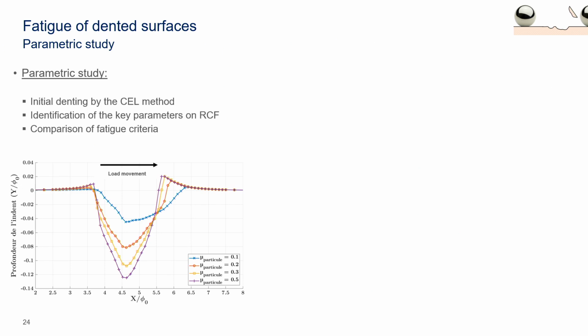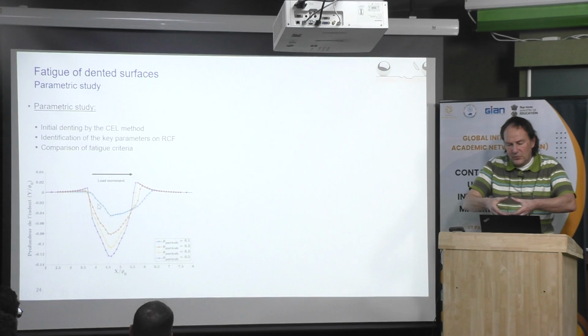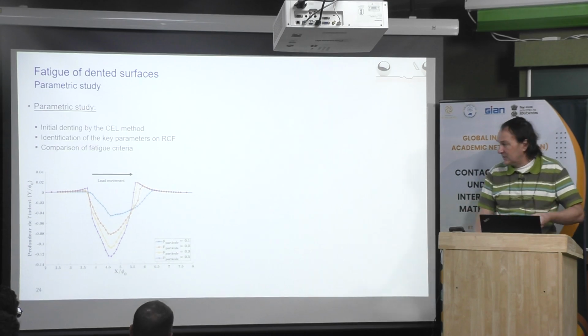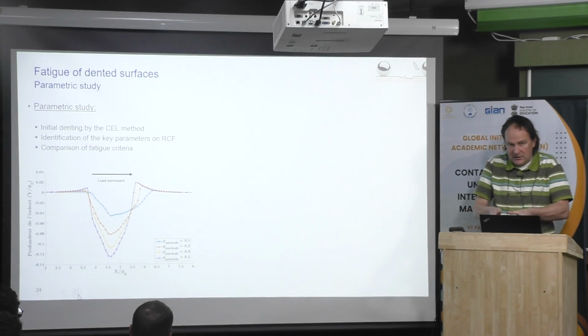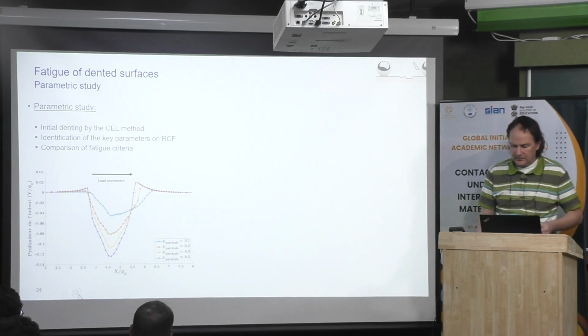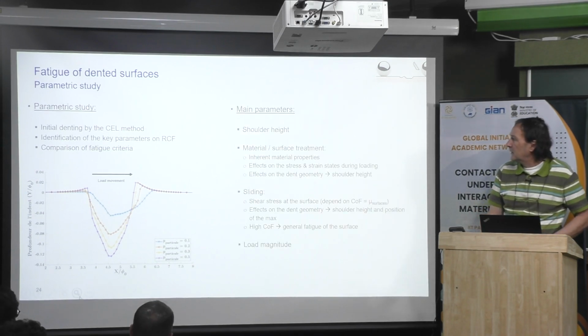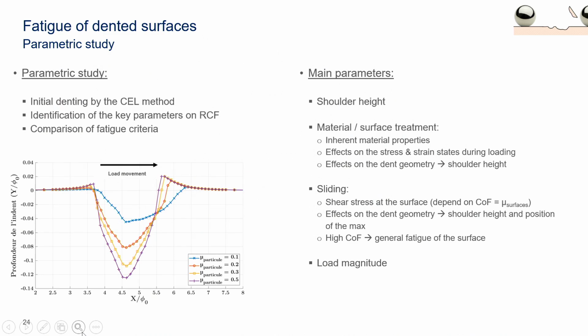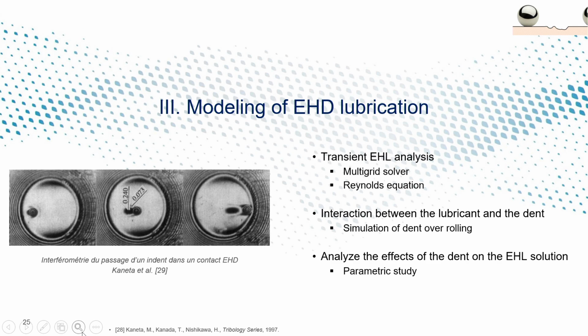This is the effect of the friction coefficient between the particle and the body. As I said before, when the friction coefficient is very low, the particle will flow away when it is deformed, and when it is very high, it will be blocked. Then the dent will be deeper. This is a summary of the main parameters for the debris denting and the consequence on the fatigue life of the material. Now I would like to go back to EHL.